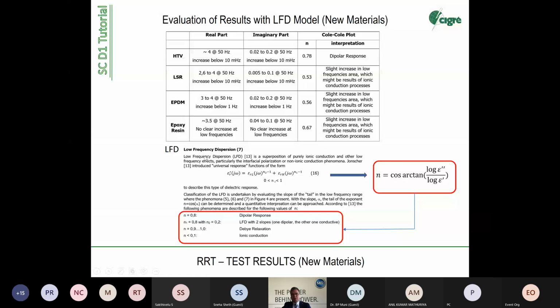We have taken out this equation for evaluation. It's a double mode equation. So it has one part for the low frequency area and another part for the higher frequency area. So at the end, we skipped the higher one. We just looked into the lower one. Then you only have one N, it's sufficient, because we have almost no effect here in the high area, but 99% here in the low area. And thus we work with just one N.